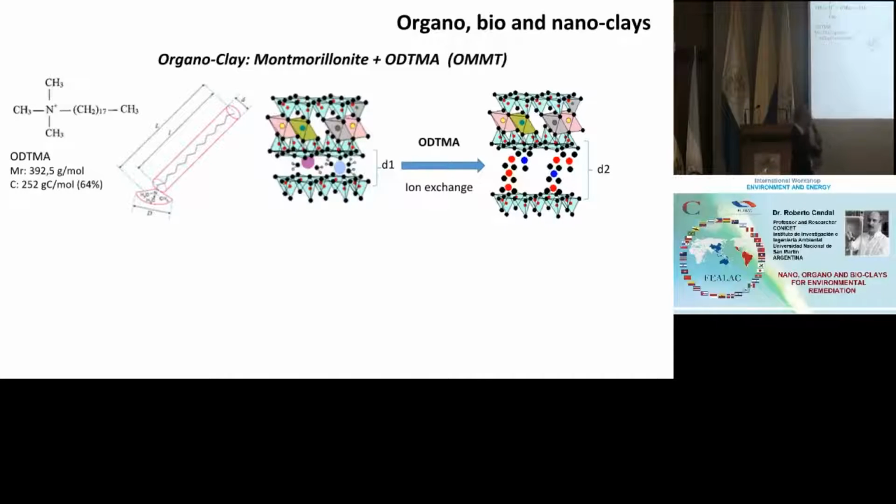It makes kind of layers, and because of electrostatic interaction, because of cations, sodium, calcium, that are lodged in these interlaminar spaces, these have an intrinsically negative load, where aluminum with 3 valences replaces silicon, so there's a deficiency of positive load that generates a permanent negative load in the interlaminar area. For this not to explode, there's the presence of cations that stabilize the structure. These layers, you can make very fine layers.